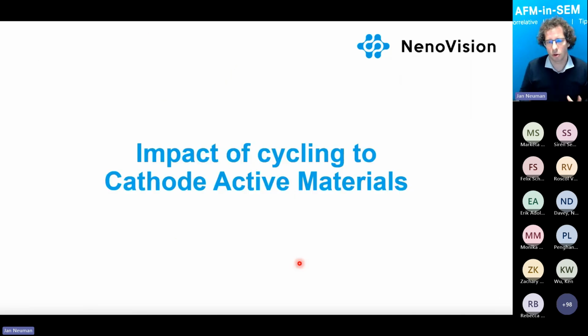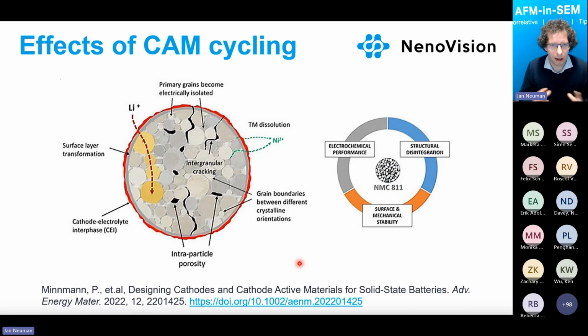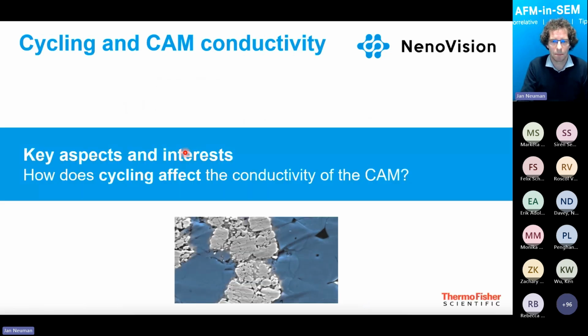So now I would like to have a look at how we can analyze the impact of cycling, actually degradation of cathode active materials. I would like to briefly remind how the cathode active material behaves during cycling. Basically the lithium ions are going in and out. It's a charging and discharging process where the lithium is going inside the cathode materials. And actually the whole particle is kind of breathing because it's changing volume, which induces internal cracks, which again affect the conductivity and the performance of the overall battery.